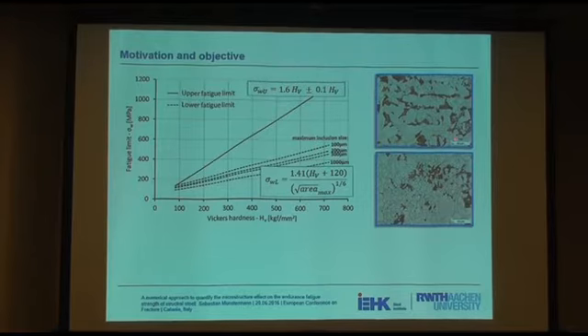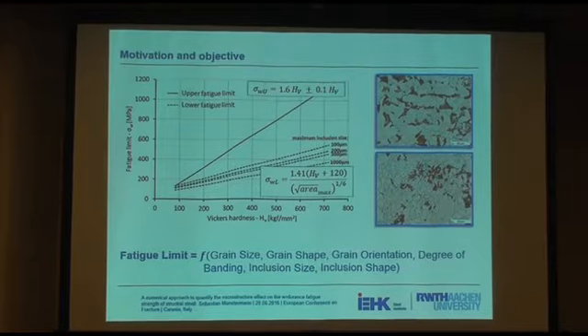In other words, according to these findings, it does not play an important role if the microstructure looks like this or if the microstructure looks like this. But both these images were made for steels of the same grades. Both of them are steels with a guaranteed yield strength of 355 megapascal. The question I would like to answer with my presentation is if we can express the fatigue limit of steel as a function of microstructural parameters like grain size, grain shape, grain orientation, degree of banding, and so on.